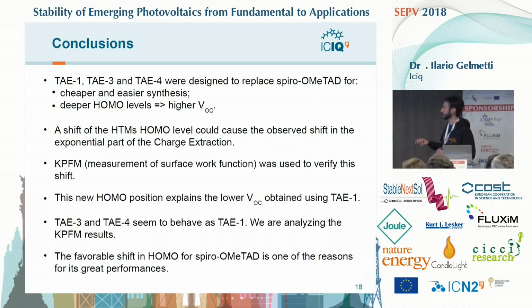A shift in the hole transporting material's HOMO level could cause the observed shift in the exponential part of the charge extraction. This was verified by Kelvin probe force microscopy, measuring the surface work function. And this new HOMO position on top of the perovskite could explain why with this novel hole transporting material we obtained a lower VOC, and could explain why with spiro-OMeTAD we still have better efficiencies and better VOC. Thanks.